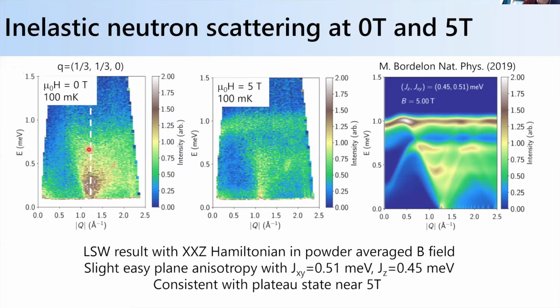Okay, so we see these excitations with no real spin wave, propagating modes that we can model within this sort of powder average data. And there's quite a lot of spectral weight up here at finite energy transfers, okay? But what we can find is that when we apply a 5 Tesla field, the spectral weight, these spin fluctuations, actually sort of condenses into the Bragg peaks of the up-up-down state. And then we also see a well-defined band of magnetic excitations here, as well as some lower energy features.